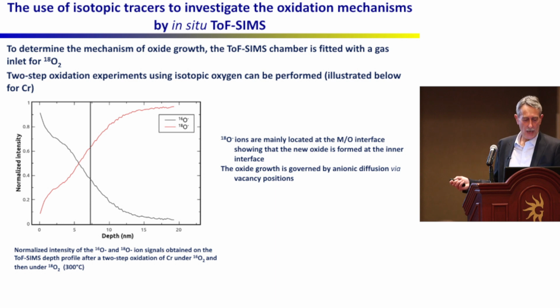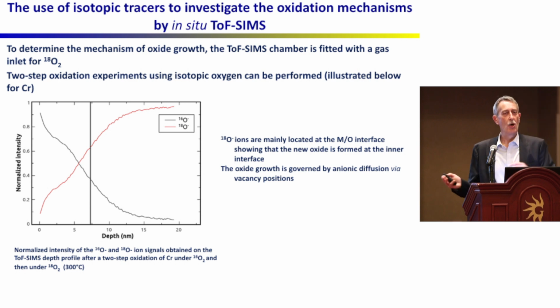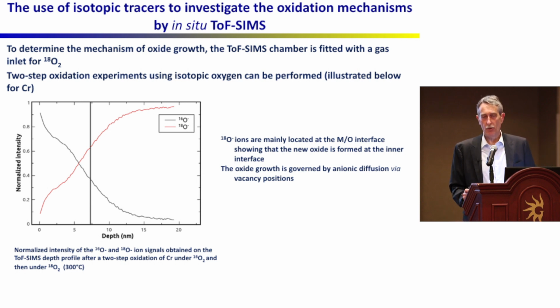So this here is an in-depth profile. This is the signal of oxygen-16 and the signal of oxygen-18 after this two-step experiment. And you see there is absolutely no ambiguity. It's very clear that you find the oxygen-18 in the inner part of the oxide. So this gives direct evidence that under the conditions of this experiment, the oxide is growing by diffusion of oxygen. And this means that we have oxygen vacancies in this oxide film. So on a pure metal, it's fairly easy with this equipment to look at problems like that. Of course, it's more difficult if you take an alloy, but it is feasible.